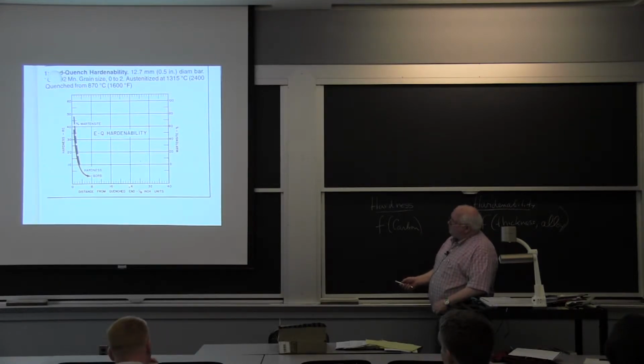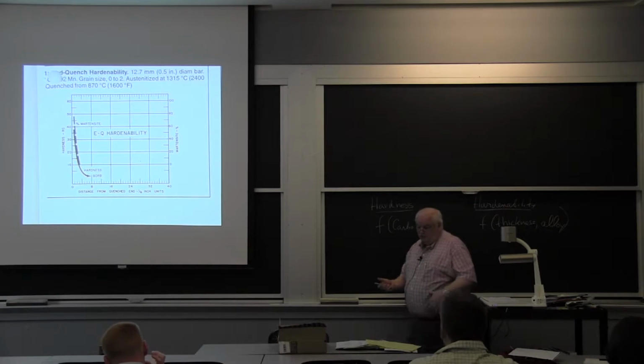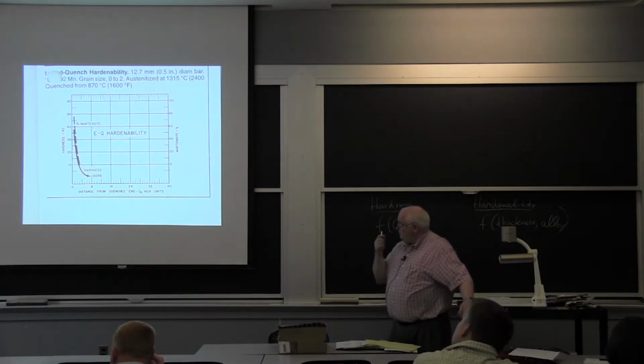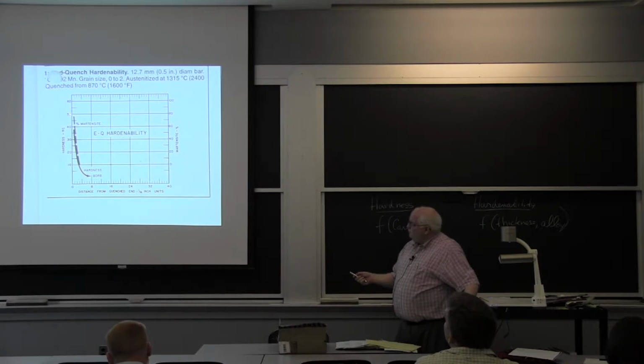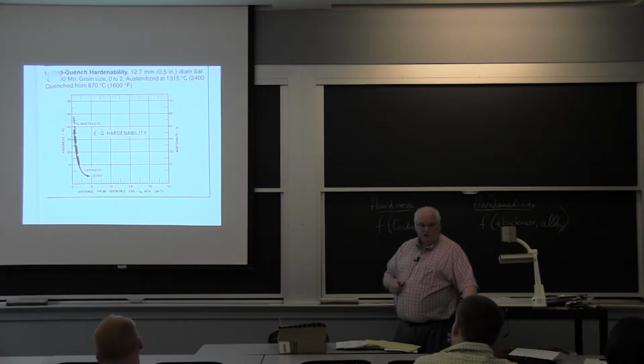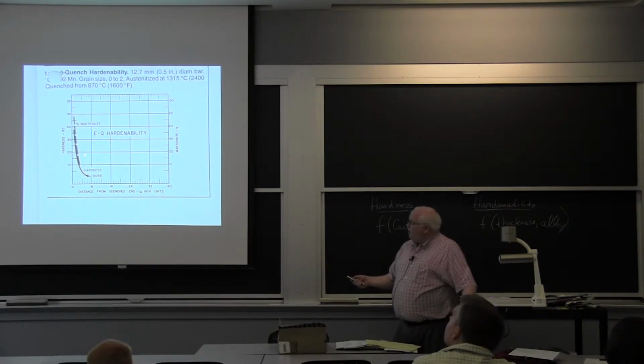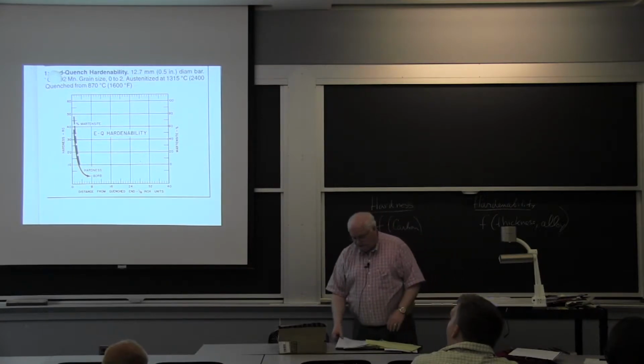this is the distance from the quenched end of a bar. So they just take a cylindrical bar, put a shield around it, and they quench the hot steel just by hitting it with a strong jet of water at one end, and they measure the hardness into the steel in 1/8 of an inch units. So you can harden a 1021 steel, which is a low carbon steel, easily weldable, a little bit higher carbon than you make an automobile sheet metal out of, but you can only form martensite to about 1/8 of an inch, or 2/8 of an inch, 1/4 of an inch deep, maximum, because the reaction is so fast.